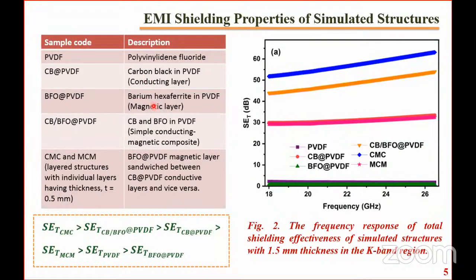For this, all our materials are polymer-based materials. Our polymer is PVDF, our conducting filler is carbon black, and our magnetic filler is a hexagonal ferrite known as barium hexaferrite. The CB/BFO@PVDF composite denotes carbon black and BFO in PVDF, that is the simple conducting magnetic composite. CMC and MCM refer to conducting-magnetic-conducting and magnetic-conducting-magnetic composites, where a magnetic material is sandwiched between two conducting layers, and a conducting material is sandwiched between two magnetic layers, respectively.